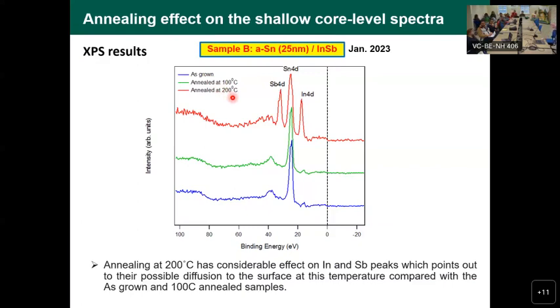In the end, you want to use these samples in devices, okay? And you want to be sure about their stability and performance at different temperatures. It's not about the physical status of the material, like whether it melts or doesn't melt. That's not the target. You need to understand the electronic structure. What's happening there? How do the electrons interact with each other and with their surroundings? So here we show an example, the material is stable from the electronic structure point of view up to 100 degrees Celsius. And then some changes happen.